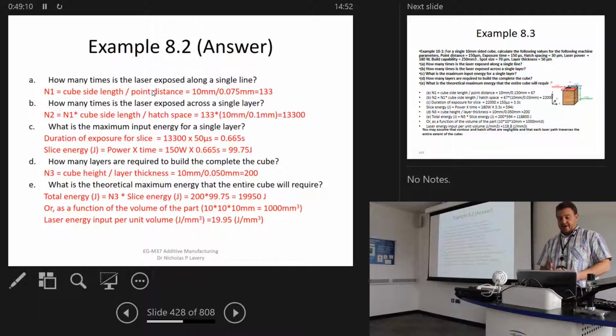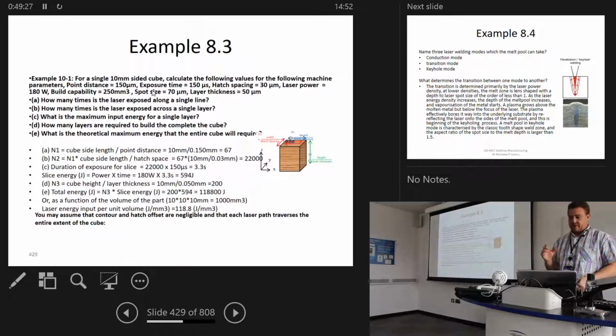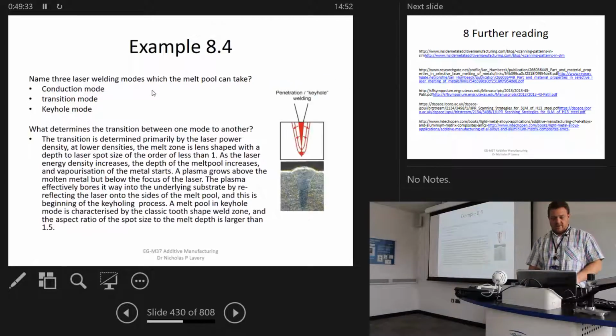Now, that is for the entire 10 millimeter cube, so to get the laser energy input per unit volume, we take 19,950 divided by 1,000, which is 19.95 joules per cubic millimeter. There's another example in there, which I won't go into now, which does exactly the same thing but with slightly different dimensions. I'll leave you to go through that.